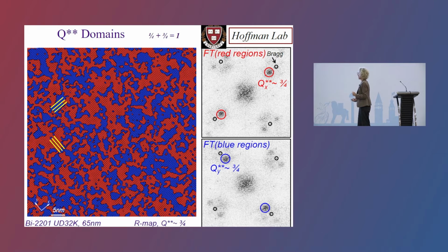So this is a visualization of scanning tunneling microscopy out of Jennifer Hoffman's group. This is BSCCO 2201, so a single layer BSCCO. It's an underdoped sample with transition temperature 32 Kelvin. The data is taken at 6 Kelvin, so low temperature. This is a 65 nanometer by 65 nanometer field of view.